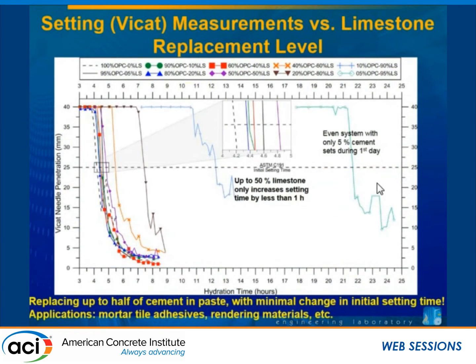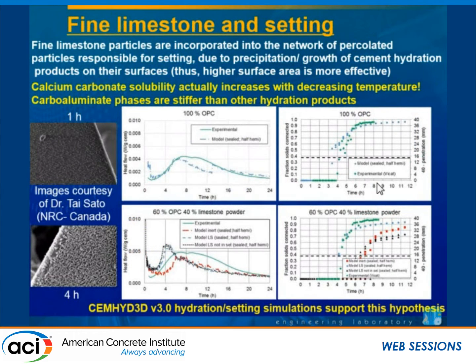This indicates that the limestone added to the mix is participating in the percolated structure that develops during setting. Looking at Vicat setting, we see this effect again — up to 50% replacement of cement with limestone gives about an hour increase in setting time, and even at 5% cement content, we still observe setting within 24 hours. Our working theory is that the limestone is providing nucleation sites for hydration products to form. A numerical model of cement hydration confirms this, showing that when limestone participates in both providing nucleation sites and setting, simulated and experimental results match well.